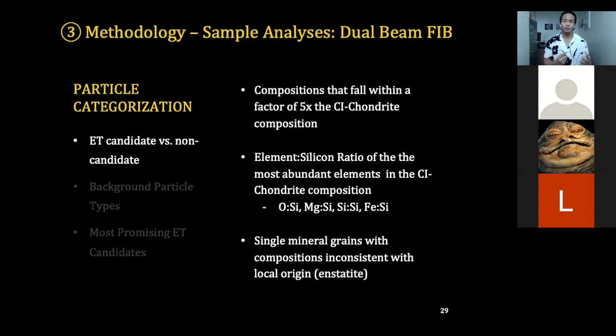We also looked at single mineral grains with compositions that are inconsistent with local origin. So in our case, it's Hawaii. And a good example of that is an enstatite particle from a prior collection effort at MLO as well, that has significantly high magnesium levels and low iron levels, inconsistent with what we would expect the volcanic particles in Hawaii should have.